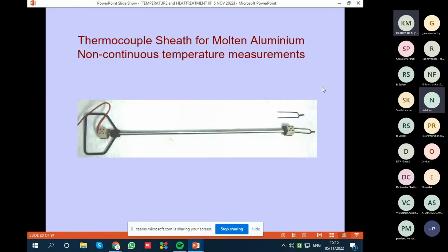For aluminum temperatures, if you want to measure the temperature once in a while, non-continuous, this is the thermocouple used, which is a bare thermocouple. It is about 120 millimeter long. You just dip it in the molten aluminum, and it quickly determines the temperature and passes it on to the instrument, which I showed you earlier. The range will be different. Aluminum temperature range is lower, but you can measure temperature using this technique.